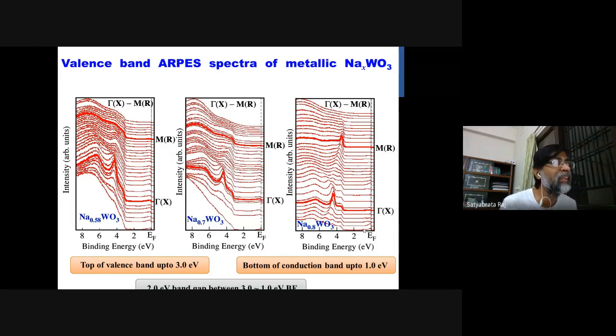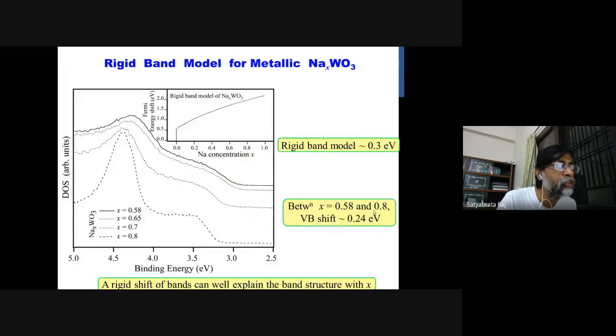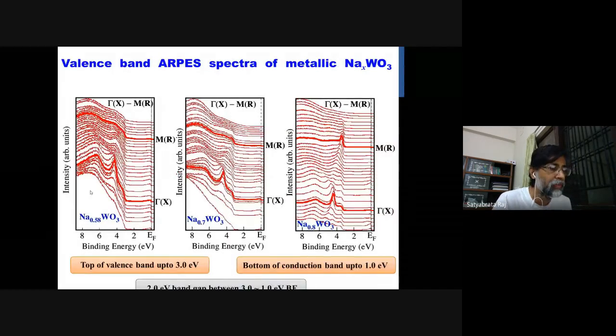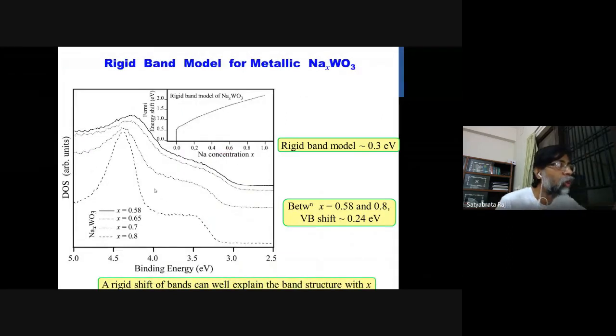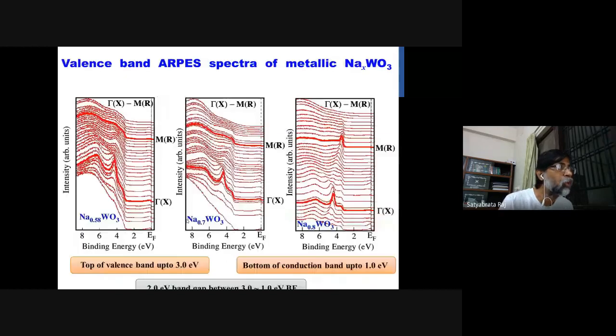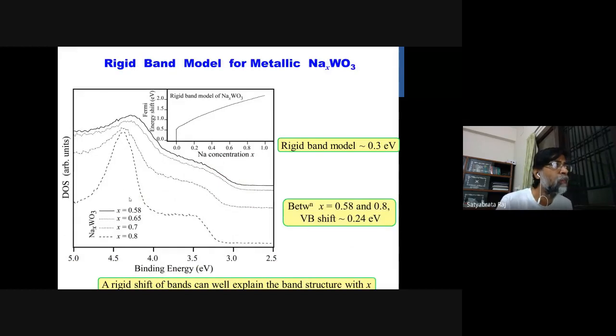whether we can assume the rigid band model or not. So to do that, I have taken the spectra at the gamma point of each sample, and then we have compared them starting from the EF. You can see that in the rigid band model calculation, as soon as you put sodium concentration, your EF shifts, and this is the shifting amount you can see. And experimentally, the 4.5 eV peak, which is a very sharp peak, we can take as a marker, and we can measure the shift between the 0.8 and the 0.58, and experimentally we found that it is 0.24 electron volt, whereas the rigid band model says that it should be around 0.3 electron volt.